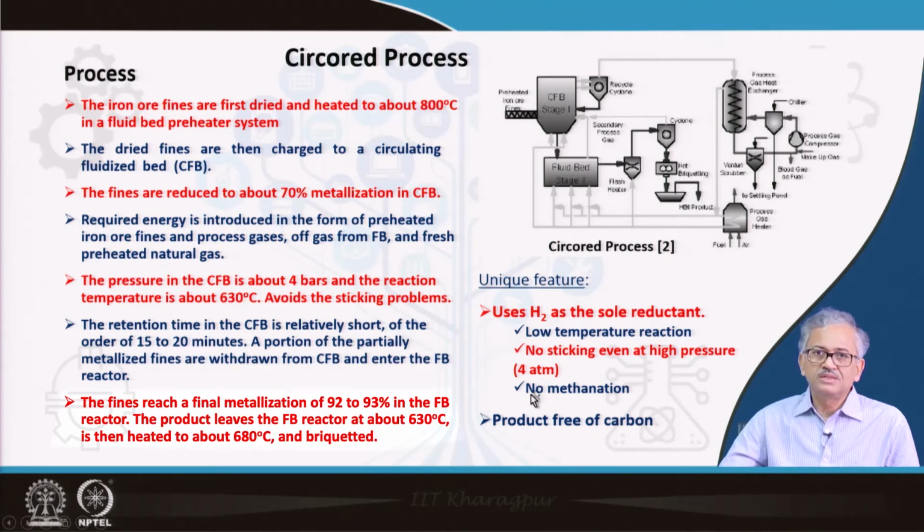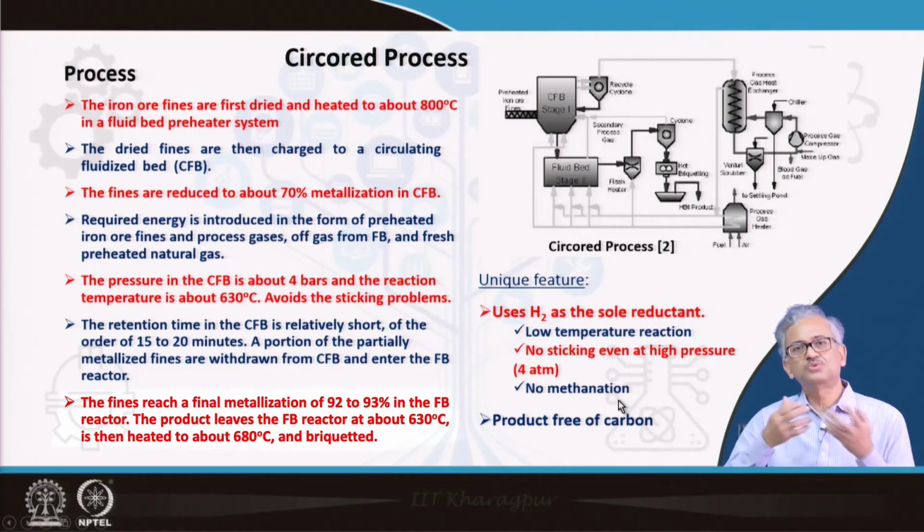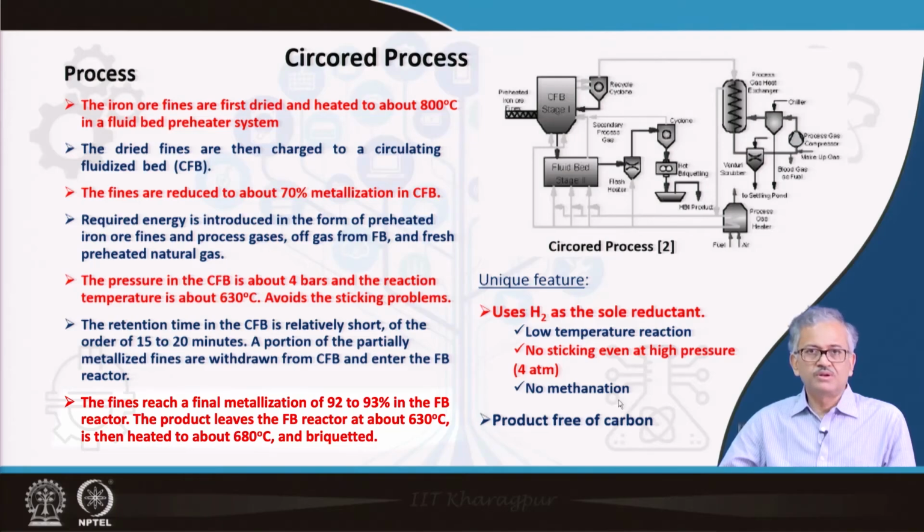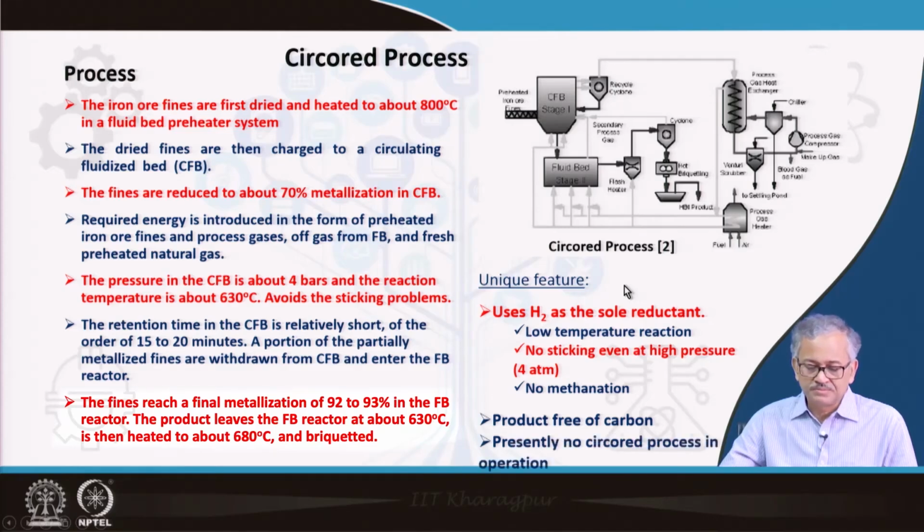And no methanation has been found, because the reducing gas is totally hydrogen, so there is no chance of methanation in the absence of CO. Interestingly, the product is free of carbon, because there is no CO and no source of carbon in the reducing gas, which is purely hydrogen. So the DRI is almost pure iron.